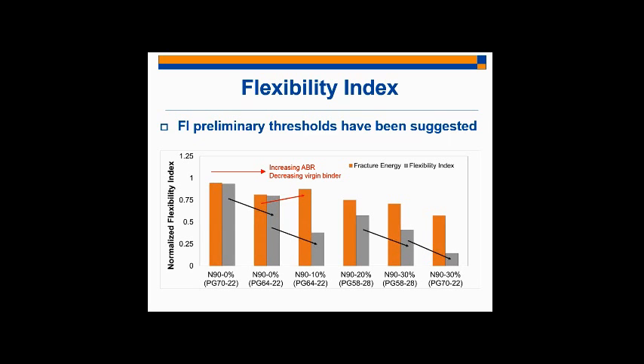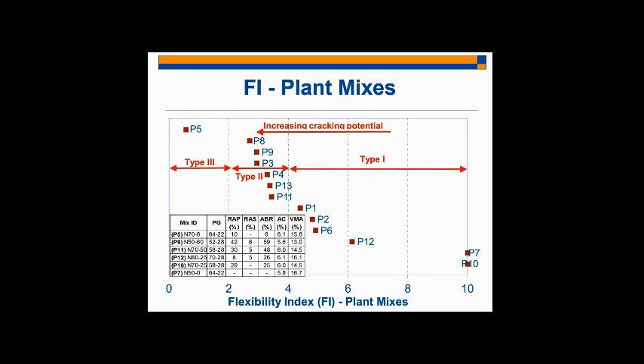And so with this in mind, we've proposed preliminary thresholds to be used for distinguishing between different mixtures after running the results through the flexibility index. So the following slide is just a presentation of all of our results from our plant mixtures. And so we have a lot of mixtures plotted on this figure. And what you can see here is, on my x-axis I've got the flexibility index values. We've tested all these mixtures, run them through the flexibility index we proposed, and looked at where they fall on this spectrum.